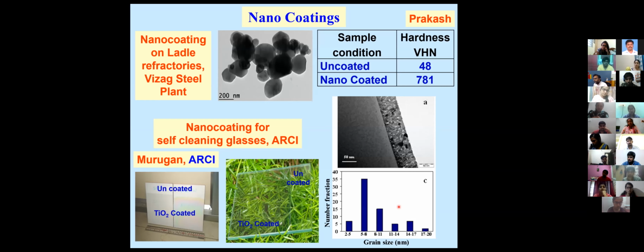We said, just simply give a nano coating on those bricks. This is exactly what Prakash worked on with me when he was a postdoc in my group, before joining Madras University, and he was able to demonstrate with his own intellectuality that we can simply give a nano coating on these bricks and increase the hardness from 48 Vickers hardness to 780 Vickers hardness. And we were able to demonstrate that you can increase the life of these refractory bricks almost 2 times. Okay, double the life, which is very important.